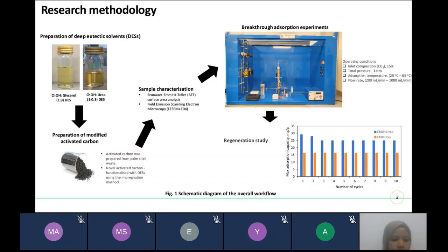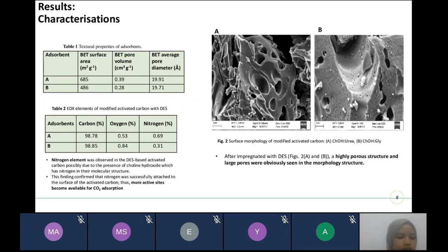Thirdly, the novel adsorbents were characterized for their textural characteristics and surface morphology using BET surface area, FESEM, and EDX. Lastly, a study on breakthrough adsorption and regeneration performance. As can be seen in Table 1, A and B refer to adsorbents modified with choline hydroxide urea and choline hydroxide glycerol. The BET surface area and pore volume of DES-based activated carbon with choline hydroxide urea were higher compared to the adsorbent modified with choline hydroxide glycerol.